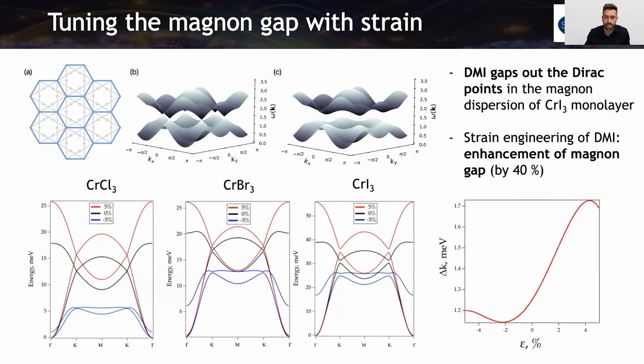But the important thing is the difference between the iodide and the bromide and the chloride, and that we can reproduce it using a zero parameter model. In this case we are not introducing any parameter.